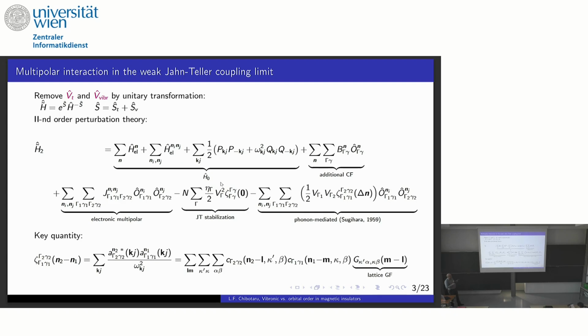So it is clear that if you have, say, no vibrational coupling between sites, this quantity will be zero. So this is how it's expressed. I wrote this expression just to show that this is a standard thing which you can obtain from the DFT calculation of phonons. You obtain the phonon spectrum, you obtain the polarization vectors and frequencies, and you can calculate this lattice Green function. And then you calculate easily these mediation factors.